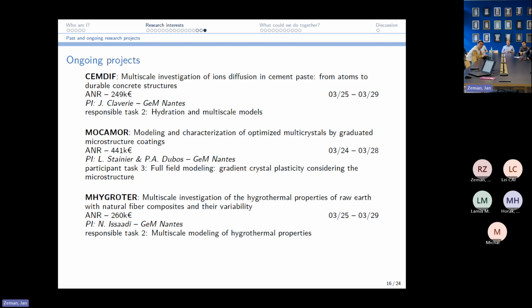Okay, and some more recent projects. Again diffusion in concrete, but here we go to the atomistic scale to see what this interface effect on the nanoscale pores is, using molecular dynamics. And we have already very nice results about that. Then we have an ongoing project on very thin metallic sheets, which have a reduction of their yield strength because they are so thin. It's because you have only a few crystals in the thickness of the sheet, so you have a lack of dislocation density, and then it can be healed by depositing a very thin layer of metallic crystals on top. But to model it properly, we need some gradient crystal plasticity model. So we're trying to do that with fast Fourier transform. And then I will be involved in a project related to the hygrothermal properties of raw earth composites with biofibers, which are used in traditional building.